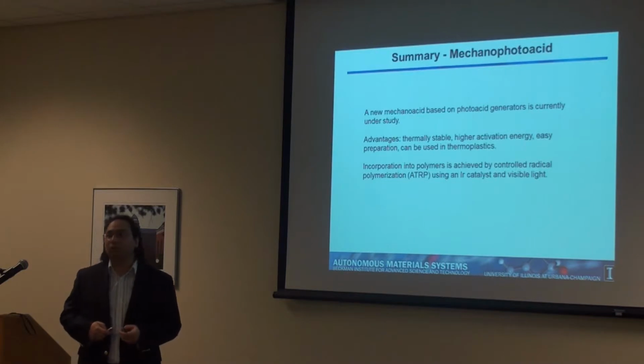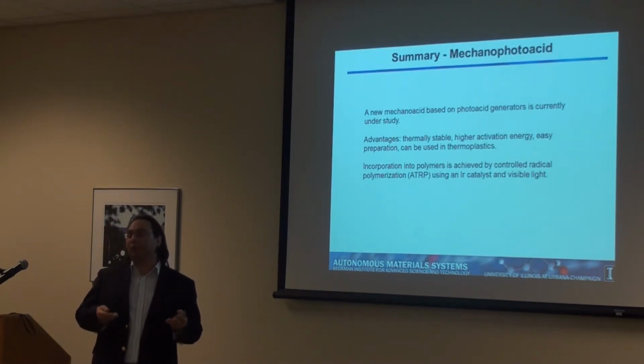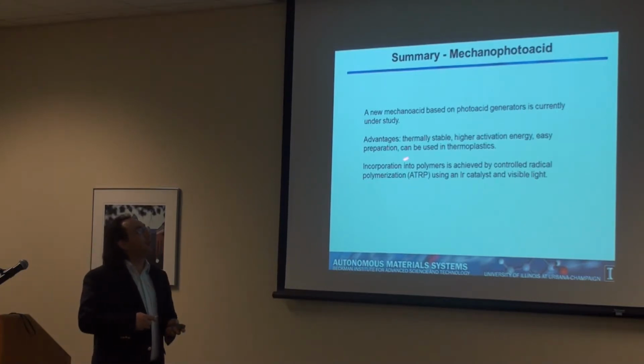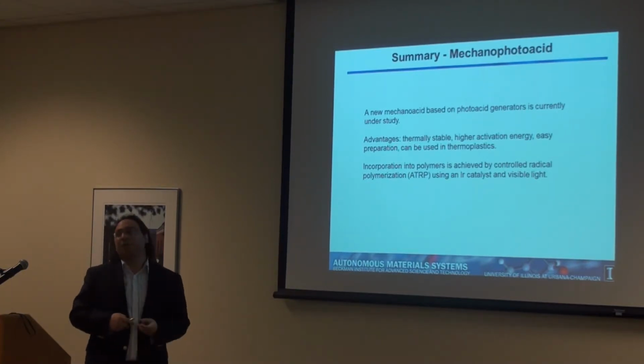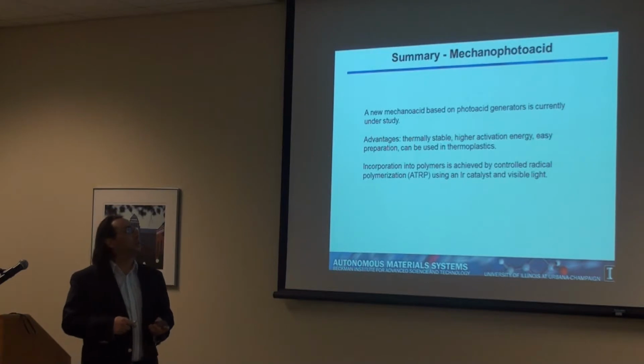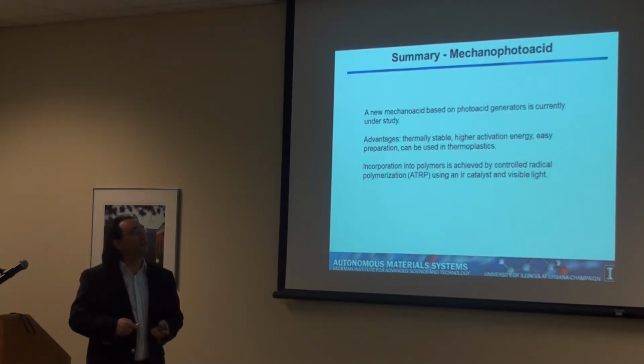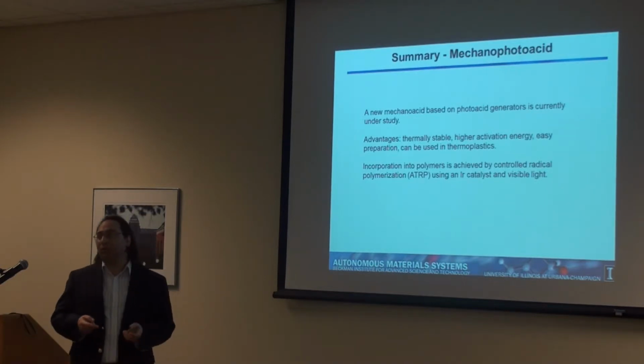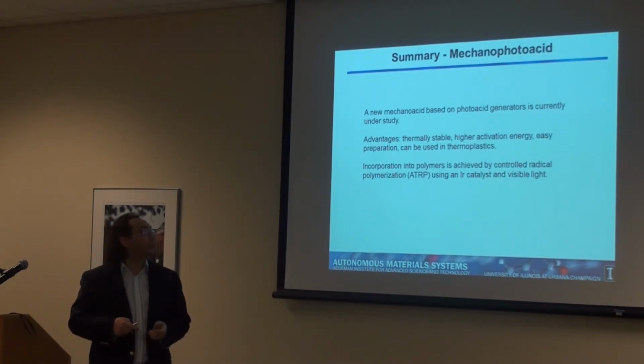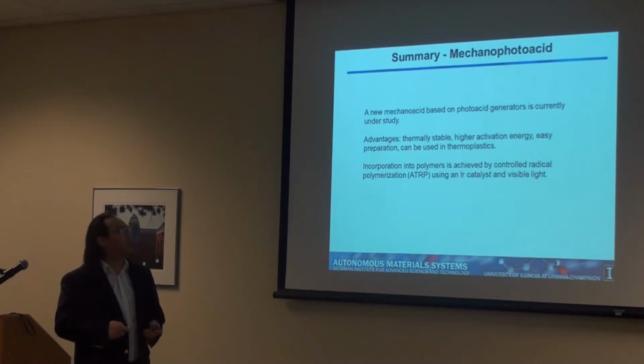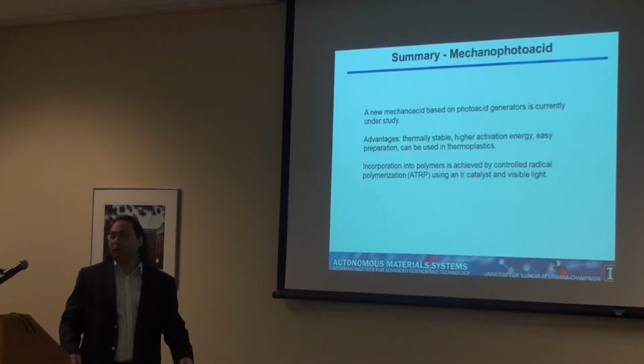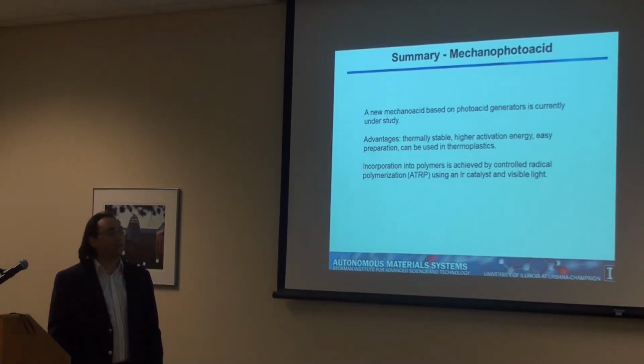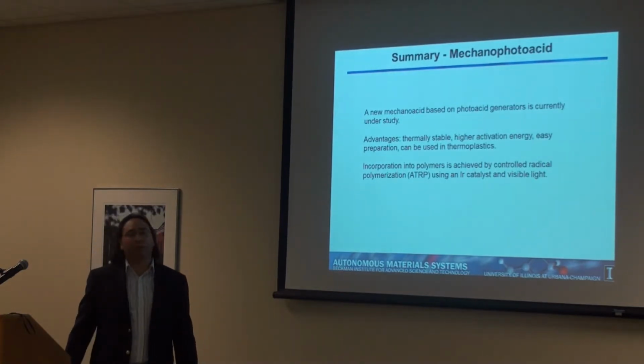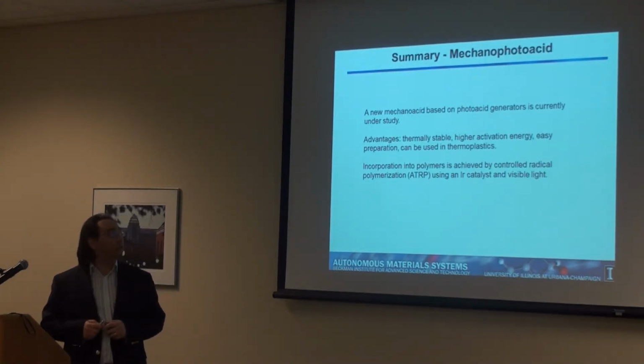So this is our second generation mechanoacid. I still have not tested it mechanically, it's undergoing, but basically this one has several advantages over the first one. It's thermally stable, it has a much higher activation energy, it's very easy to make, and it can be used also in thermoplastics. The first one cannot be used, and we can incorporate it to a huge quantity of different polymers just by using ATRP, using this iridium catalyst.